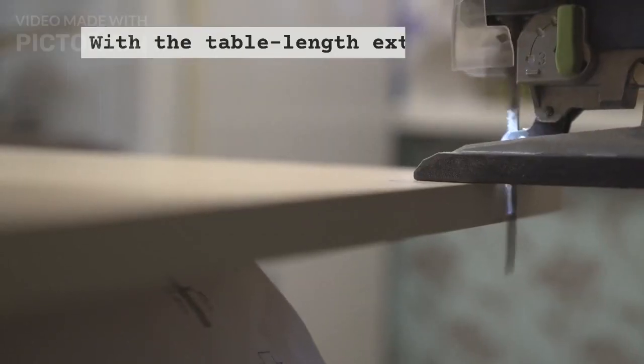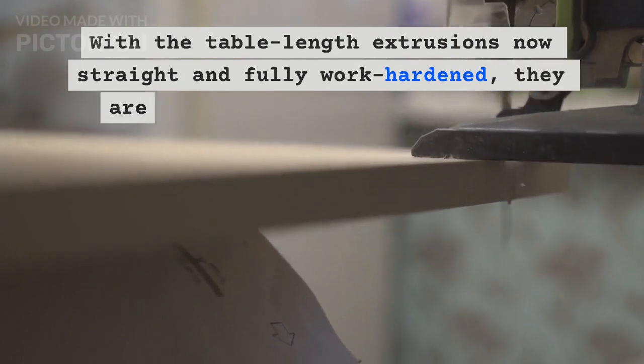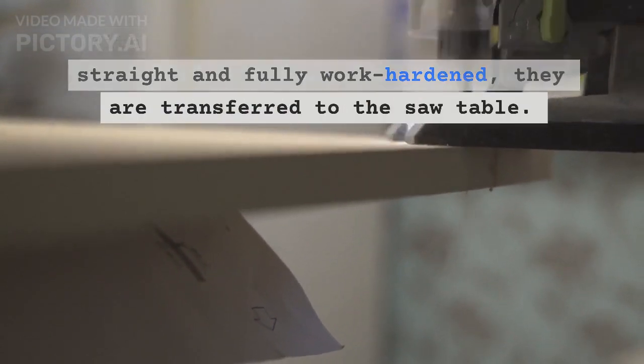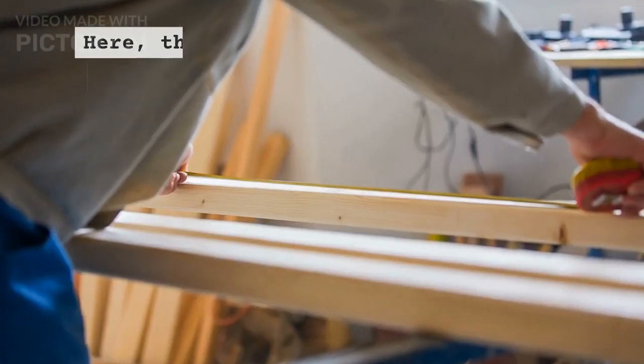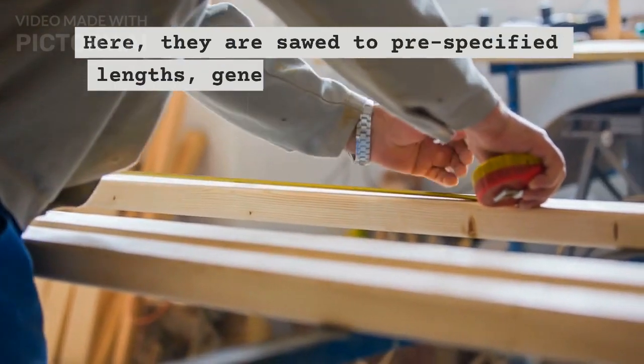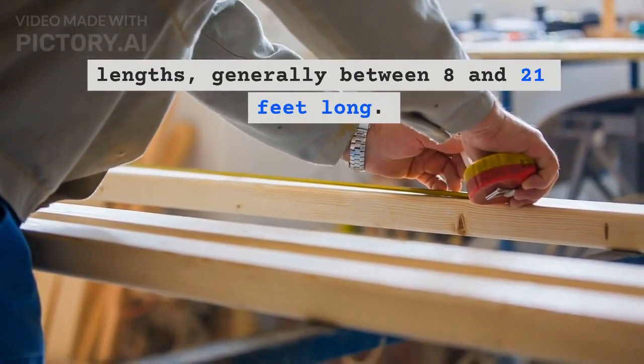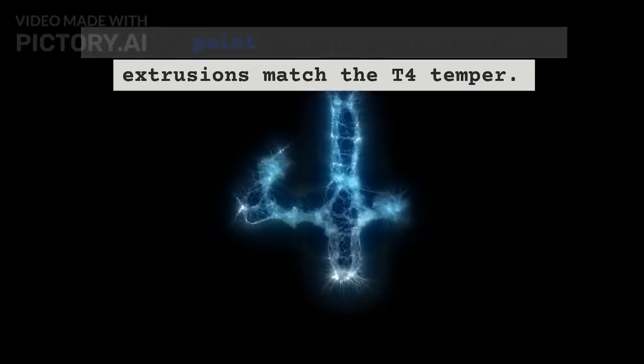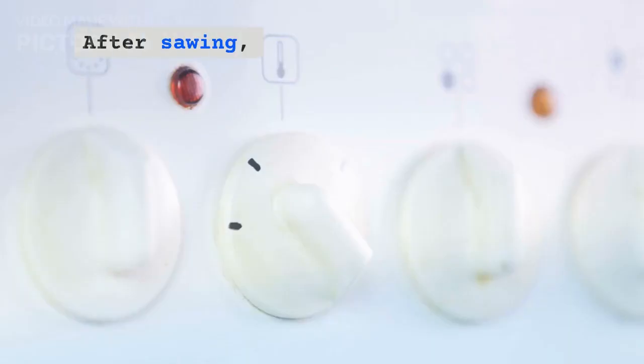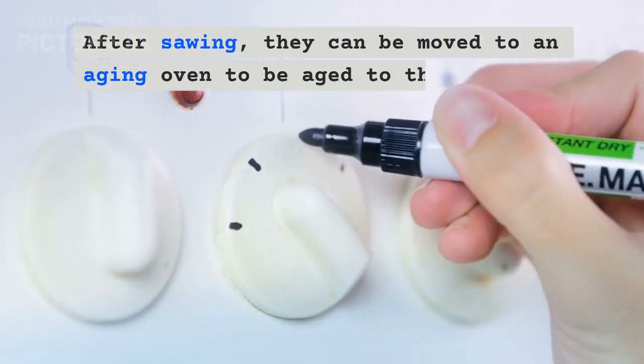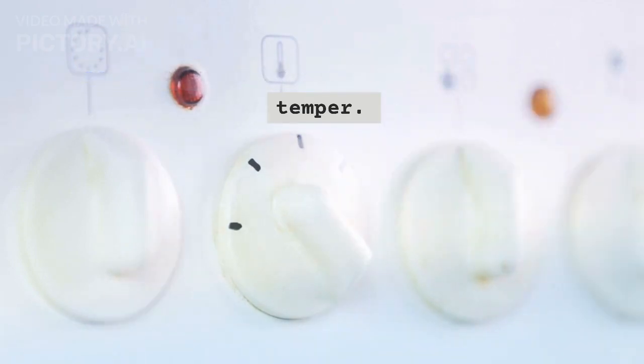Step 10. Extrusions are moved to the finish saw and cut to length. With the table-length extrusions now straight and fully hardened, they are transferred to the saw table. Here, they are sawed to pre-specified lengths, generally between 8 and 21 feet long. At this point, the properties of the extrusions match the T4 temper. After sawing, they can be moved to an aging oven to be aged to the T5 or T6 temper.